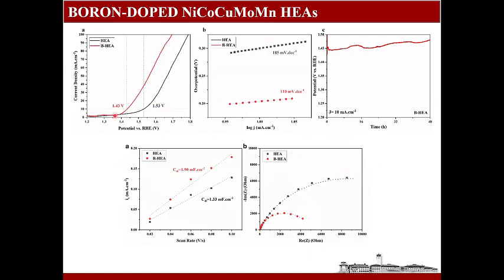So the boron doped high entropy alloy exhibited a much lower overpotential than the non-doped high entropy alloy, as you see, and the Tafel plot is also lower for the boron doped one, and the stability is quite high. So we did a 48-hour stability test, and although there are fluctuations, it's quite stable. And again, boron doping decreases the resistance of the material according to the impedance spectroscopy analysis.